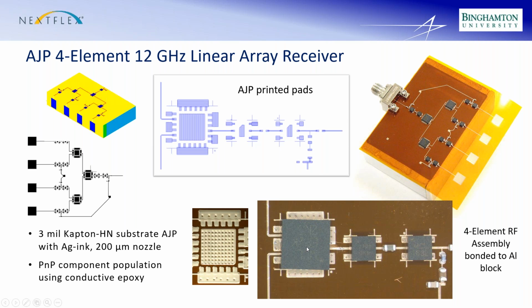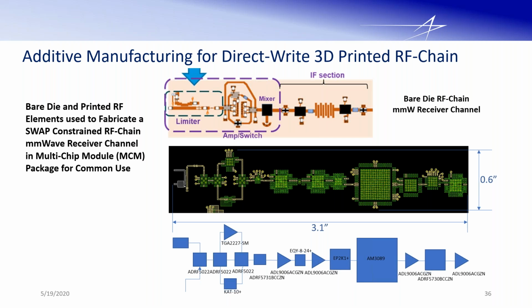So we assembled that. The assembly went okay. We had some interconnection issues, so we're still trying to get good data from the antenna lab testing. But for the most part, it printed nice. We did the pick and place. Again, we had some interconnection problems to the device that we're trying to sort out right now. But when we do that, we'll get this into the chamber and do our antenna testing. So here where I work, we have a complete anechoic chamber, and do all the pattern testing, the RF pattern testing.